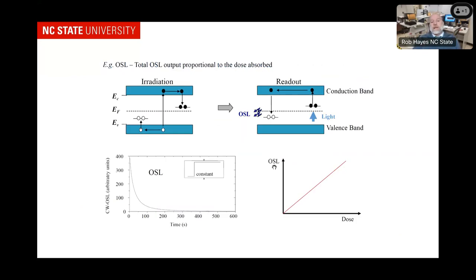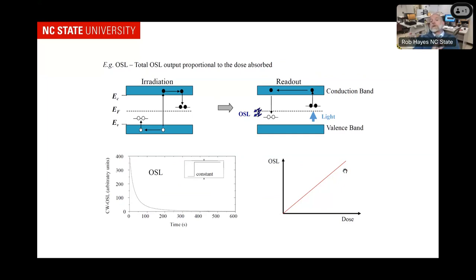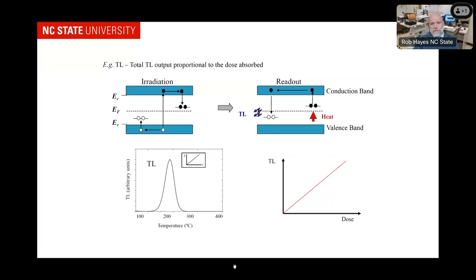The signal we're looking for during recombination is generally a decaying exponential for each site. If I have multiple sites, I'll have multiple decaying exponentials. For small doses, as the dose increases, the number of trapped charges will increase, and the OSL signal generally increases linearly with dose because the probability of trapping an electron is proportional to dose — until the traps start to become full, at which point it becomes a saturating exponential. For worker dosimetry and things like that, this is generally going to be a linear response.